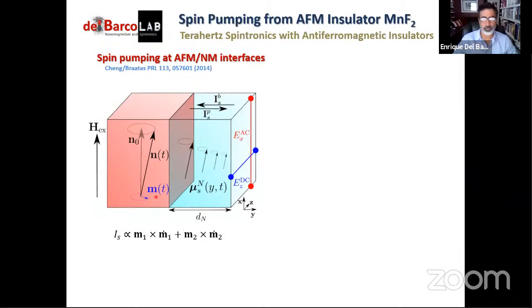And they did a kind of simple analysis to begin with by separating the two sublattice magnetizations and calculating the spin current, the spin pumping that you would expect from it in this fashion. And then after some realizations, taking into account that the two sublattice magnetizations are the same, and the same thing happens for the dynamics, the time independence of these two. So when we rewrite this equation in terms of the Néel vector or the staggered magnetization, we can derive the spin current as a function of the Néel vector, right?